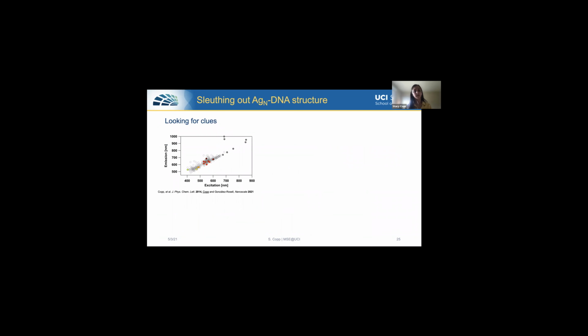So one important step in using these for nanophotonic applications is understanding what actually is the structure of the silver cluster. And until recently, we didn't have an actual atomic map of how the DNA attaches to the silver cluster. So we looked for clues based on how the color of the silver cluster trended with the size of the cluster. And I've shown you this plot before, but if we take a minute and look at it more closely, you can see there's actually a group of data points here, and then another group of data points here, and there's not too many data points in this region here.